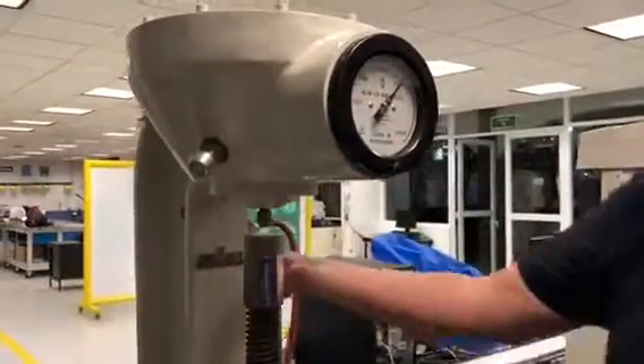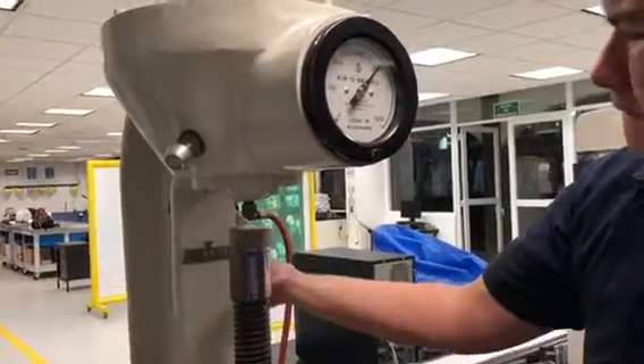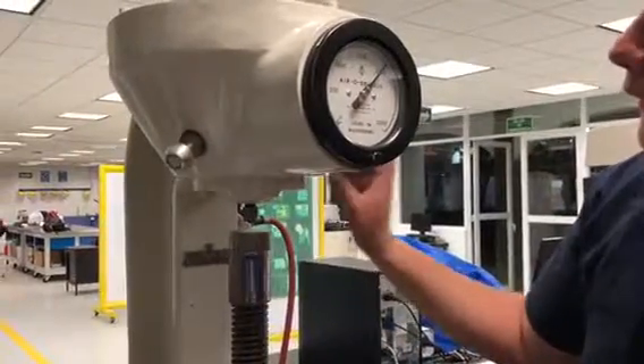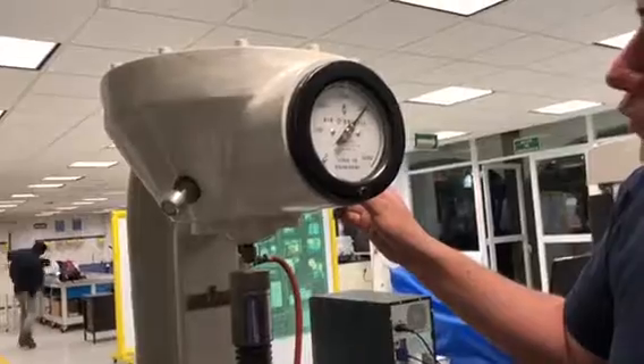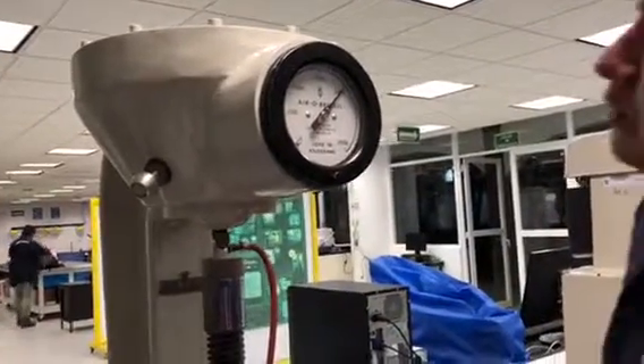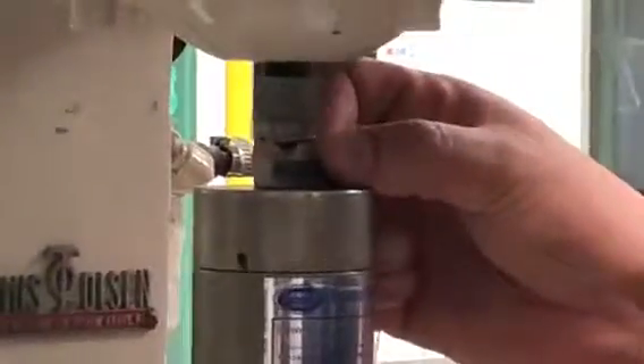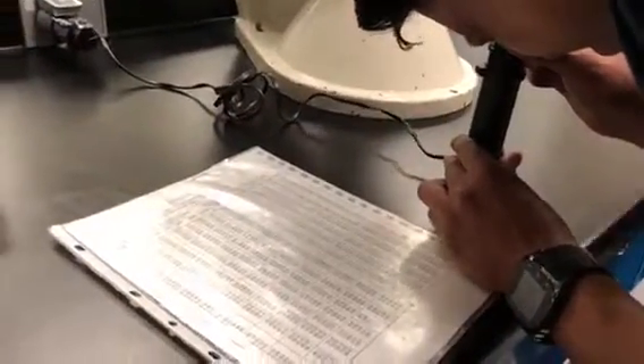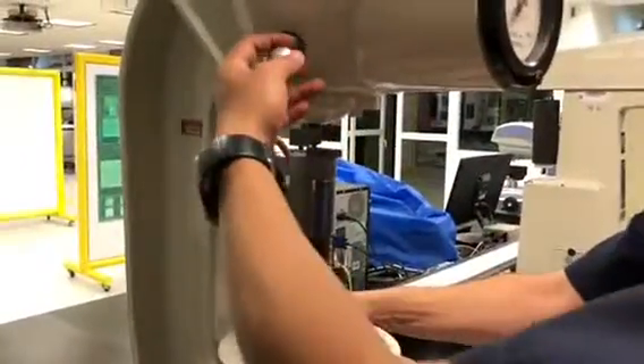For the Brinell test, an indentation of 2000 kilograms is applied on the metals. The first step is to calibrate the load. Then, the 10 mm spherical indenter is actioned in the central part of the metal's surface during 15 seconds. The diameter of the indentation is then measured with the microscope, and the hardness-Brinell to millimeter relation is obtained. The process has to be repeated 3 times in order to obtain an average value.